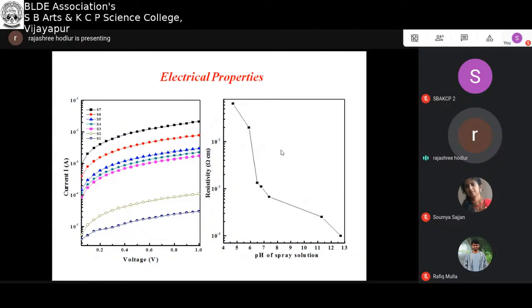So our purpose was to tune the electrical conductivity of these films. So we also studied the IV measurements. We carried out the IV measurements, and clearly we observed that by varying just the pH of these materials, we could control the electrical properties of these cadmium oxide thin films.